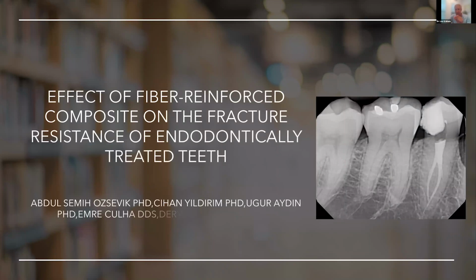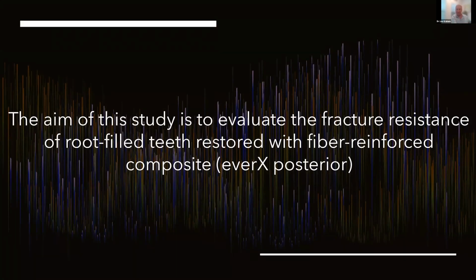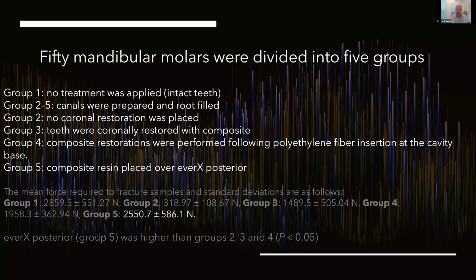So let's take a look at the effect of these fibers on the fracture resistance of endodontically treated teeth in a study by different authors 7 years ago. And this study was to evaluate the fracture resistance of root canal filled teeth restored with everX posterior, not the flow, but the posterior. But again, same characteristics. So they had 50 molars and they were divided into 5 groups of 10 each. No treatment. Canals were prepared and root filled, no coronal restoration was placed. Teeth were coronally restored with a composite. Composites were then also restored with this fiber insertion, or composites were placed over everX posterior.